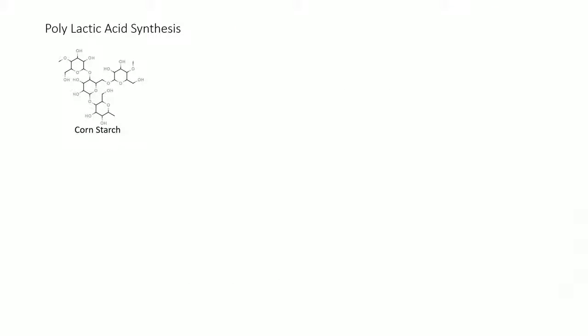Polylactic acid, like stated before, is primarily produced from corn, specifically cornstarch. Cornstarch is isolated through a washing process which removes all other products, leaving behind starch. Starch is a polysaccharide of glucose. Its monomer is isolated through a hydrolysis reaction that breaks the glycosidic bond between the glucose molecules. This process is usually run at an industrial scale to reduce starch into many glucose molecules.